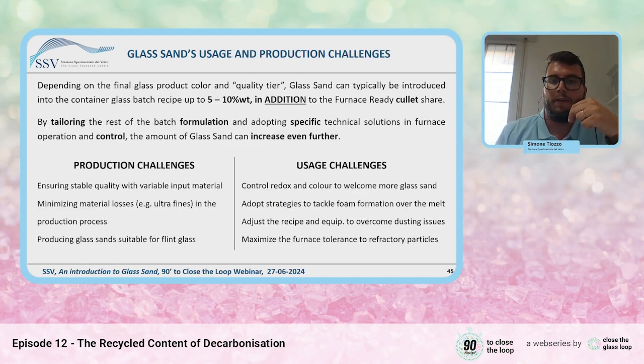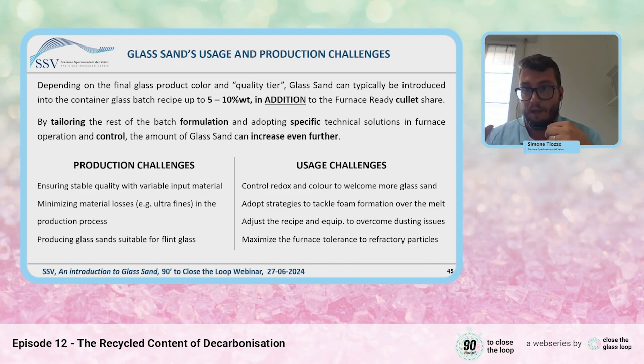But basically, if you work on that, you can even get a 5 to 10% additional recycled content, post-consumer recycled content in your glass. Of course, this requires some attention on both sides of the equation, both the producer of the glass sand, who has to master the process of producing this secondary raw material. They have to ensure a stable quality in the final product, in their own glass sand, with variable input materials, but it is basically the same story again as the production of furnace-ready cullet, because the input material is basically rejects from the same material recovered from the municipal waste.